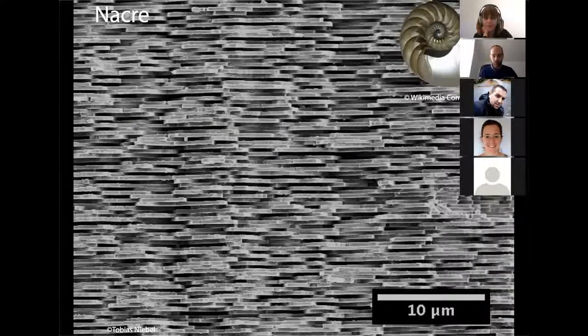In terms of microstructure, this is an SEM of nacre, and you can see that it's constituted of platelets, maybe 10 micron wide by 500 nanometer thick. And there is the mortar: the protein is just around all of these small bricks that you can see here. That's why you only have 5%, because you only need it at the interface, but the rest is these perfectly packed platelets.